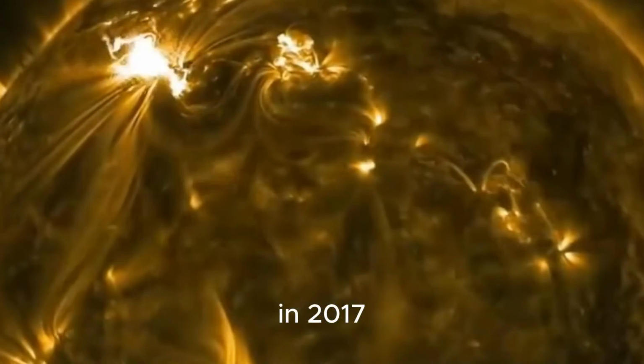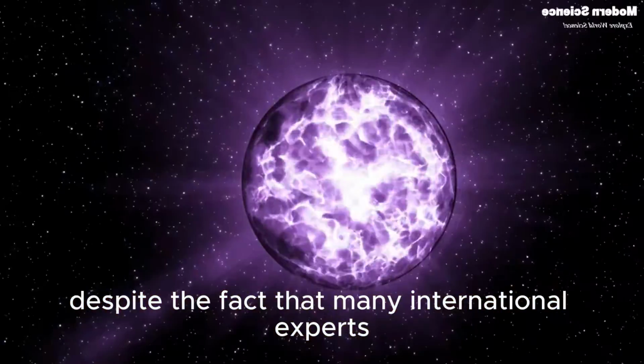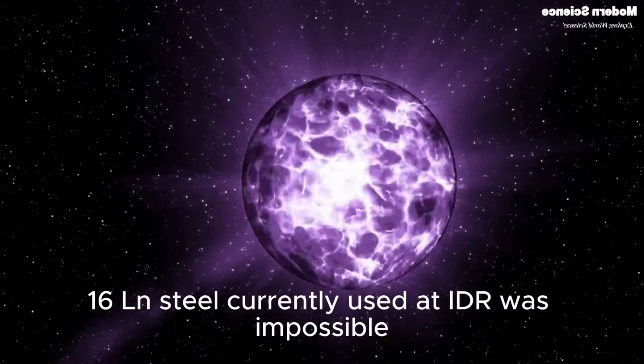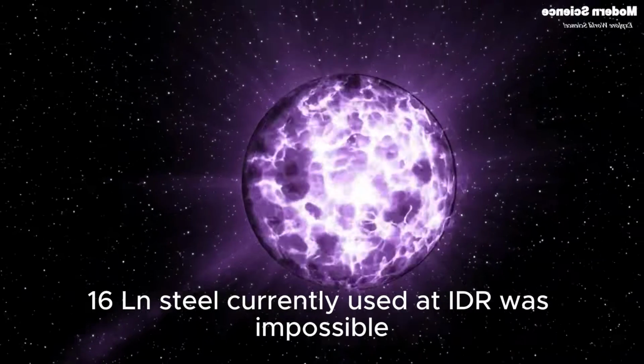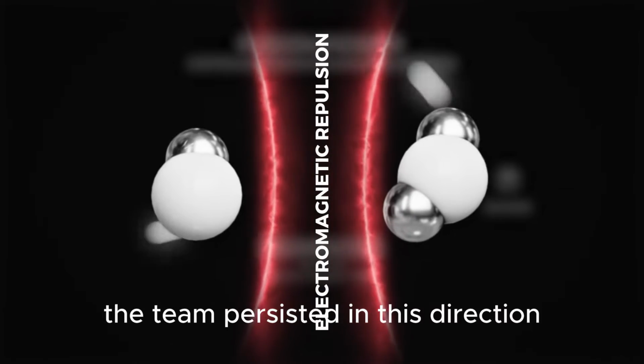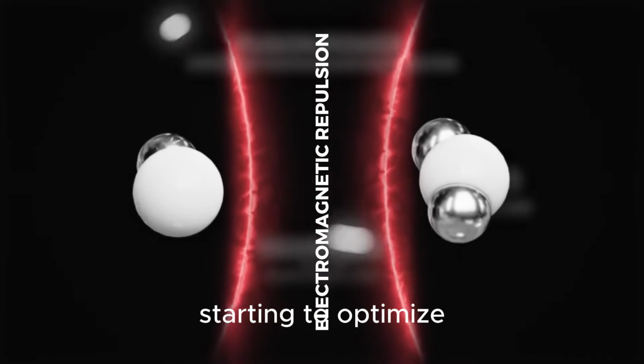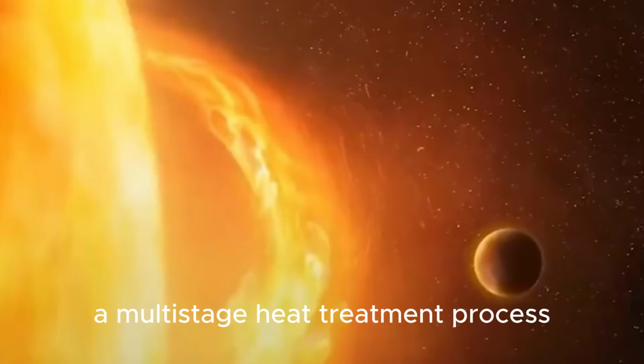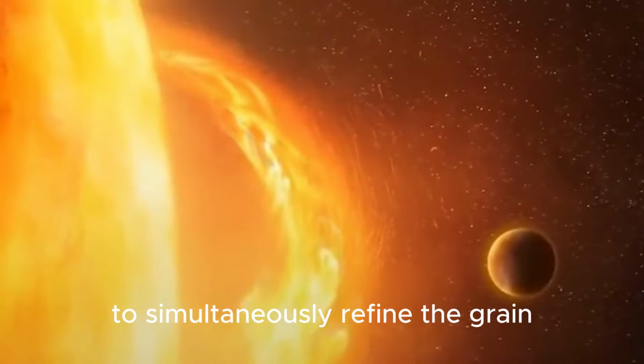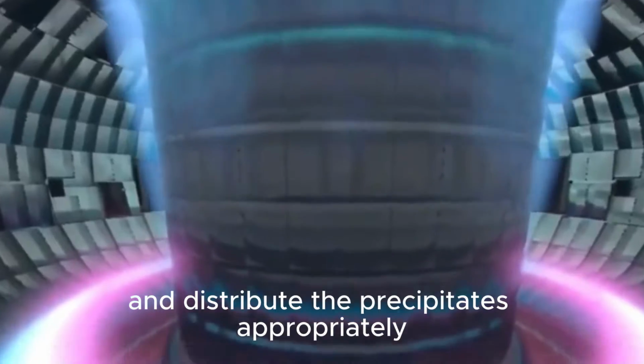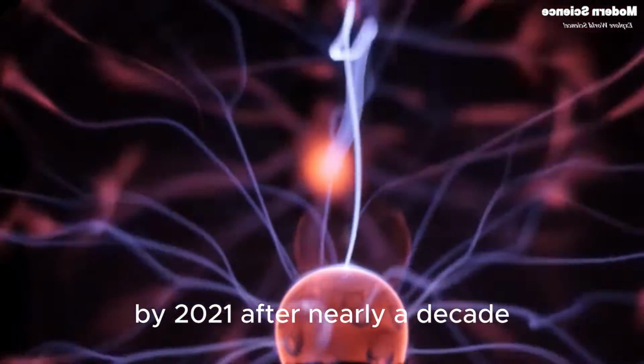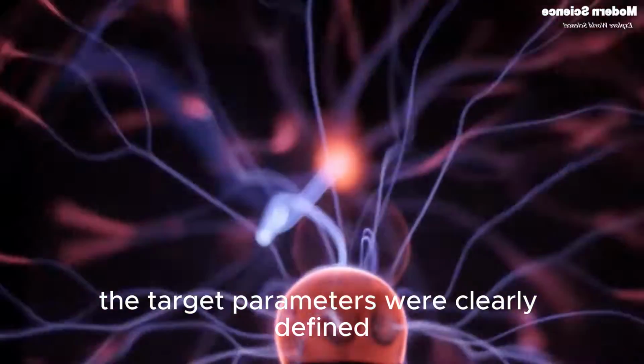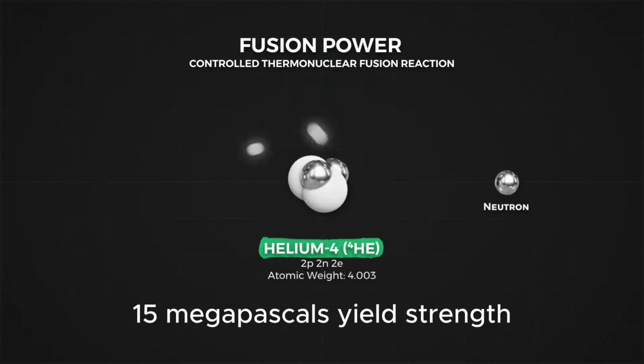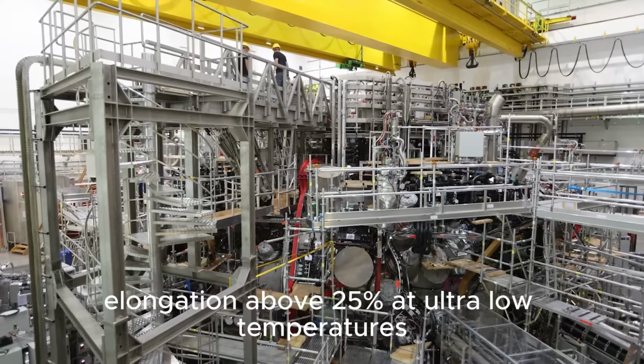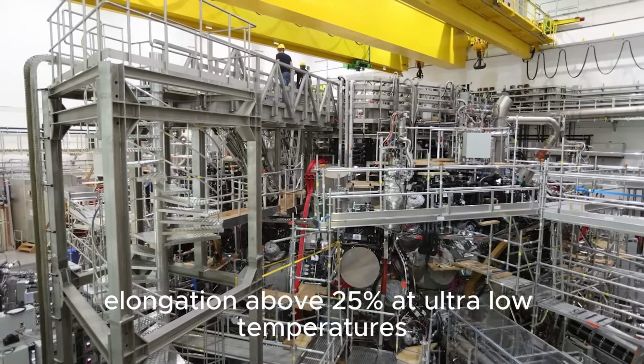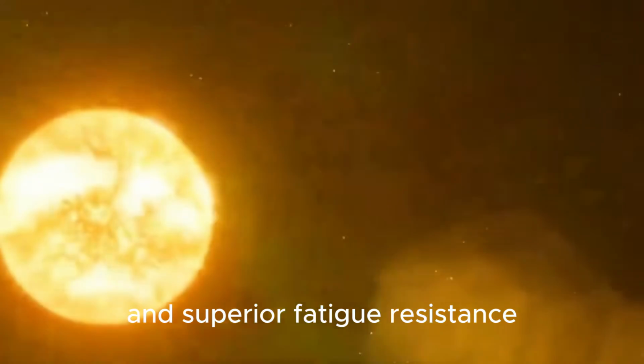In 2017, despite the fact that many international experts believed that improving the 316LN steel currently used at ITER was impossible, the team persisted in this direction, starting to optimize a multi-stage heat treatment process to simultaneously refine the grain and distribute the precipitates appropriately. By 2021, after nearly a decade, the target parameters were clearly defined: 1500 megapascals yield strength, elongation above 25% at ultra-low temperatures, and superior fatigue resistance.